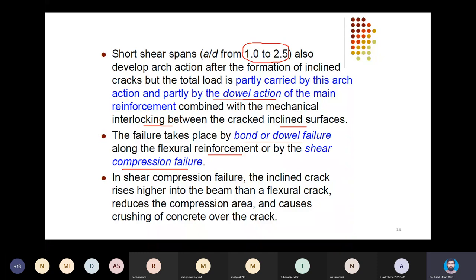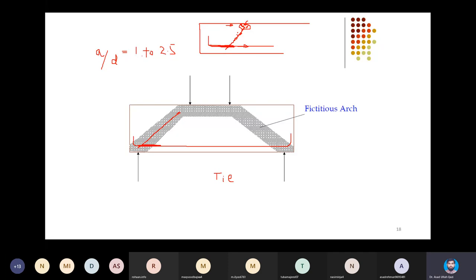In shear compression failure, the inclined crack rises higher into the beam than a flexural crack, reduces the compression area and causes crushing of the concrete over the crack. Actually, they want to mention that it has almost approached the top surface, while the flexural cracks may be over here and we still have area at this section available to develop the compression force, but the diagonal crack tip on the other side has gone even higher than the tip of the flexural crack. So consumption of the concrete block over that diagonal crack has finally caused the shear compression failure.